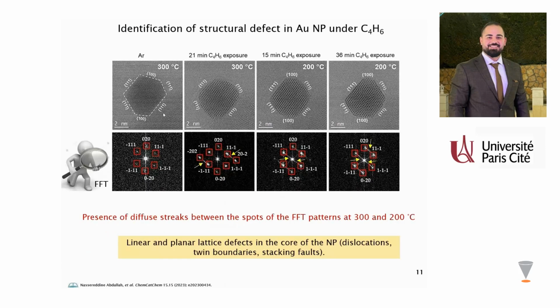It's not the end of the story, because by close examination of the Fourier transform, the FFT, of the bright field images of the gold nanoparticle, we observed the presence of diffuse streaks between the spots of the FFT patterns at 300 and 200 degrees Celsius. Based on the literature, these streaks indicate linear and planar lattice defects in the core of the nanoparticle, for example dislocations, twin boundaries, stacking faults, etc.